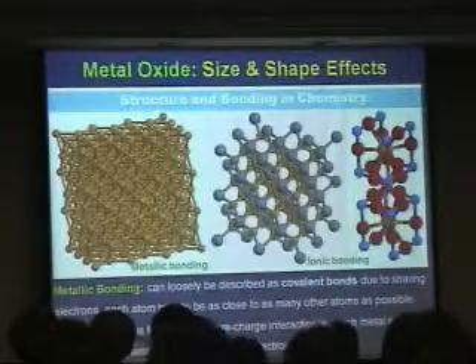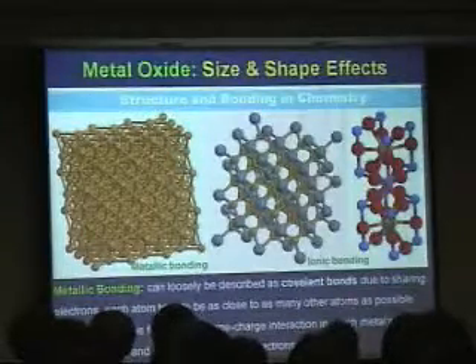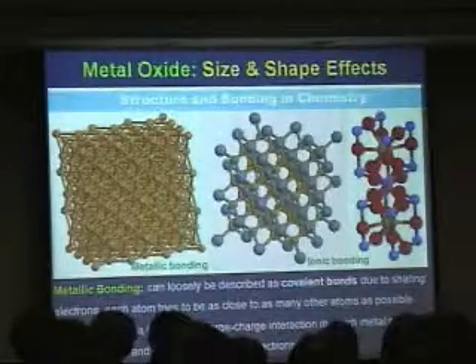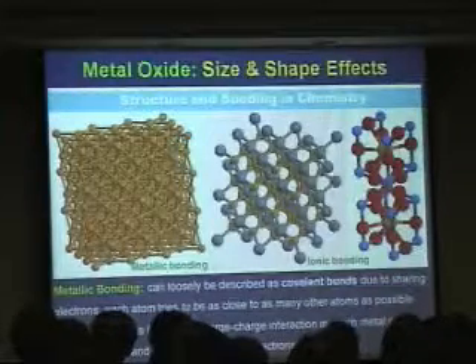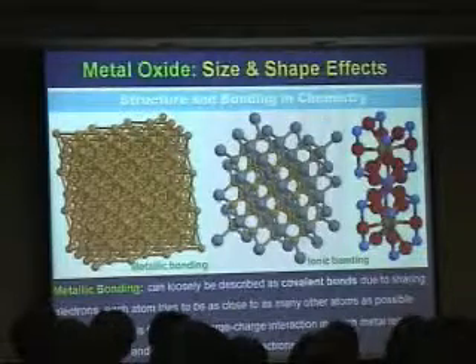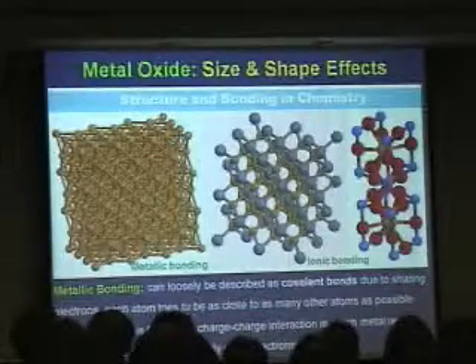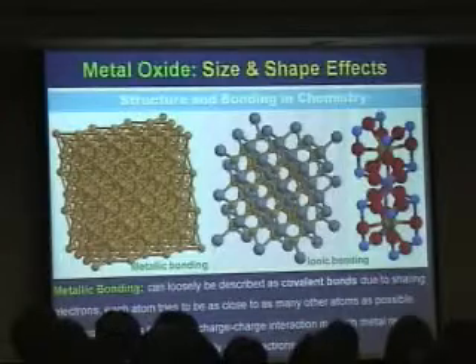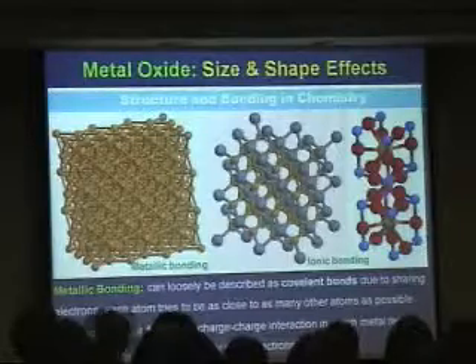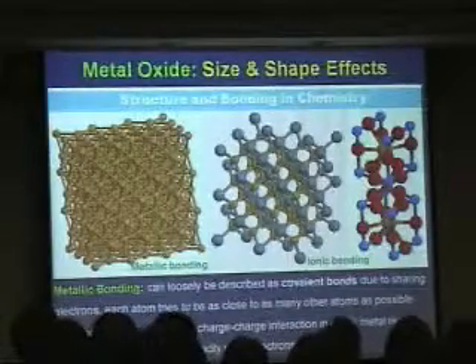But in catalysis, we still have another important player, that is metal oxide. For metal oxide, it's more difficult to control the size and shape because generally we should have the precursor followed by thermal calcination at high temperatures. This is different from the precious metal particles. Usually they obtain the metal particles in liquid solution with the protection of surfactant or template. That makes the size and shape stable. But for oxides, we must go through high temperature treatment. And actually, the bonding is chemically rather different.